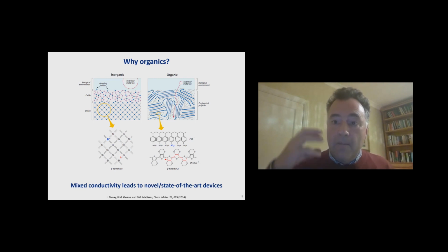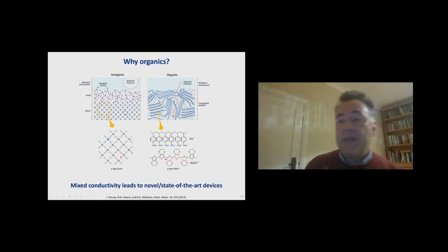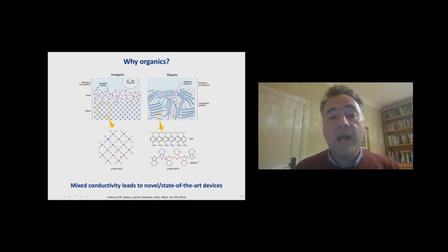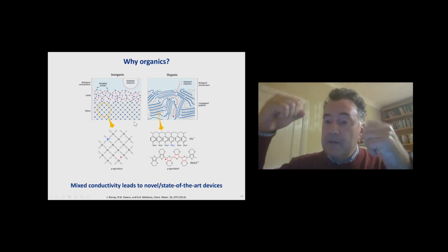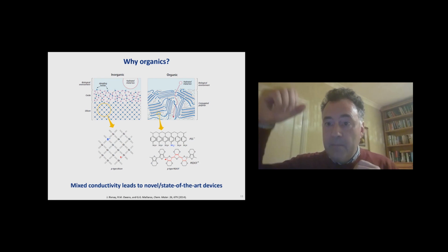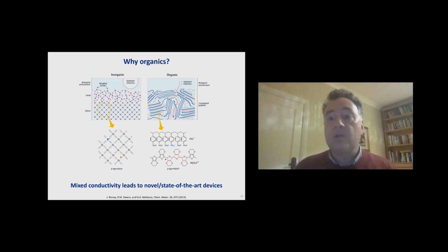You would try to make these ions interact with electronic charges, electrons or holes, inside your electrode. If you use silicon, again, the king of electronic materials, you would run into the issue that you would need to protect your chunk of silicon with either an oxide or a nitride. So this layer spaces away the ions and the electronic charge at the two sides of the interface and decreases their coupling. So the communication between ionics, the brain, and electronics, the electronic material, is just not strong enough.